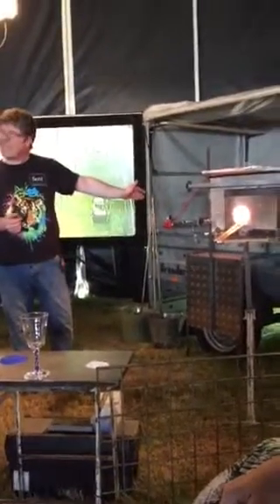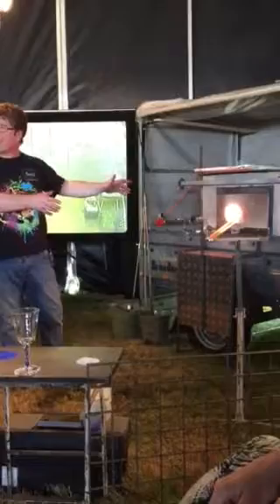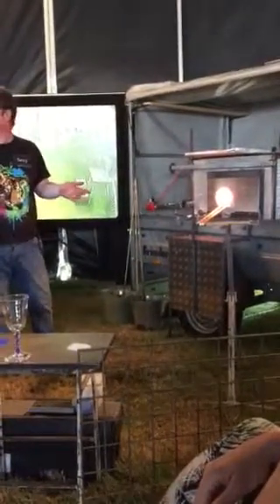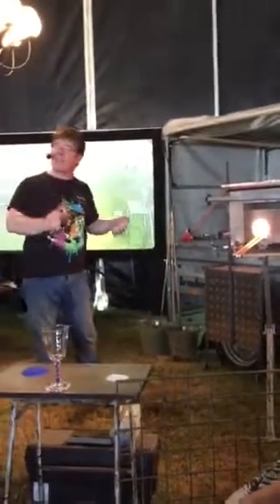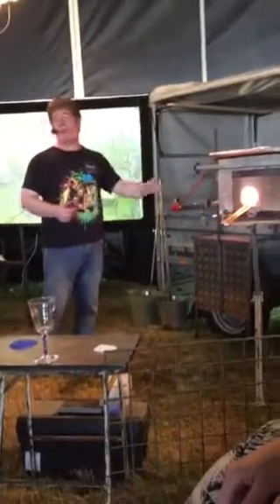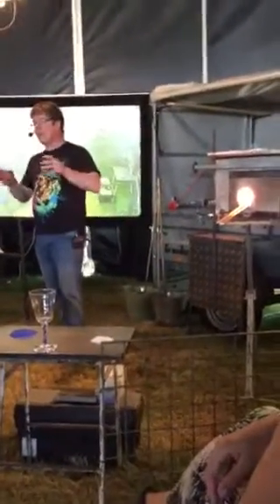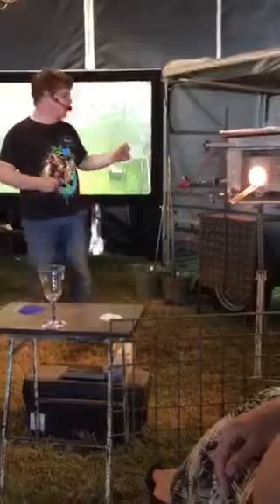Trouble is, after 6 this morning, when I came back in here, it's still 1300 degrees, and glass at 1300 degrees is like water. So what I need to do then, 6:30, is bring the temperature down to 1100 degrees, so it's a little bit thicker, a little bit easier for us to use. So that's what we've got right now.